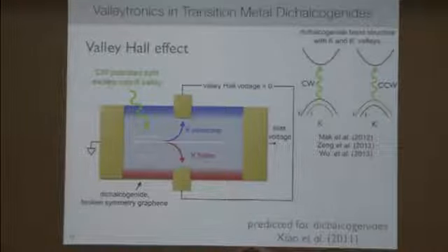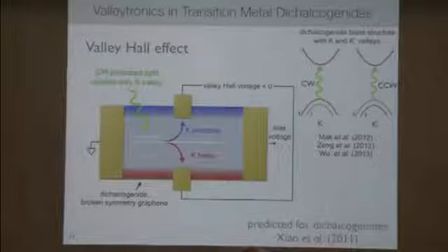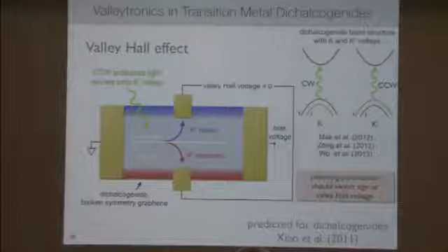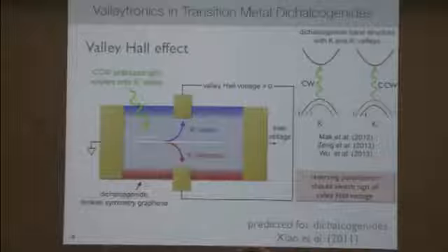But it was found last year by several groups that you could selectively excite electron-hole pairs from just one valley by using circularly polarized light. So the idea is that if you use, for example, clockwise polarized light, only K electrons and K holes get excited, and the K electrons will go to the top of the sample, and the K holes will go to the bottom of the sample. And so then you would have some valley-dependent voltage that you could measure in this case. And as a check that that is in fact what's going on in the system, you could switch from clockwise to counterclockwise light, and then the sign of this Valley Hall voltage ought to reverse.